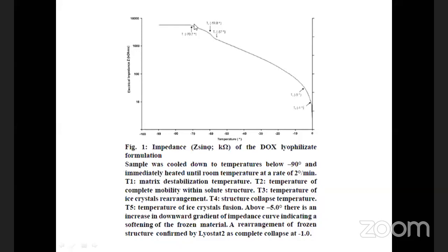So this is Lyotherm of this same formulation. If you look at these temperatures, there are 5 temperatures I have mentioned: T1, T2, T3, T4, and T5. T1 is where there is an inflection you will find. This indicates a matrix destabilization temperature, but that doesn't have much effect on the integrity of the material. T2 represents the temperature of complete mobility within the solute structure. There is a minor inflection or change in the direction of this curve. So that represents the mobility within the solute structure.